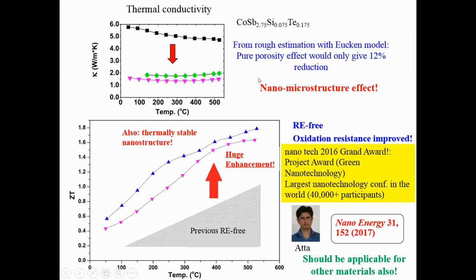And this had a very strong effect to scatter the phonon and resulted in a very large reduction of the thermal conductivity. The electrical part had only a small damage. So overall, like 100% enhancement with no rare earth. So this was a very good result by Atta.